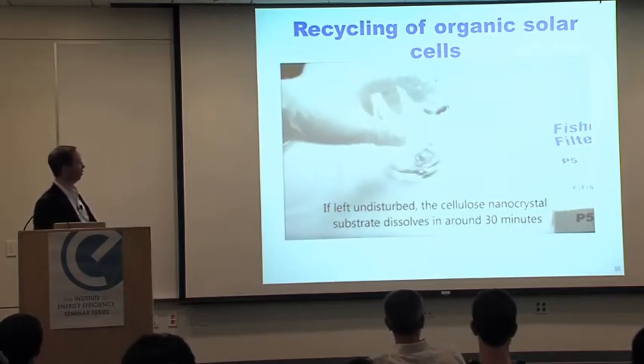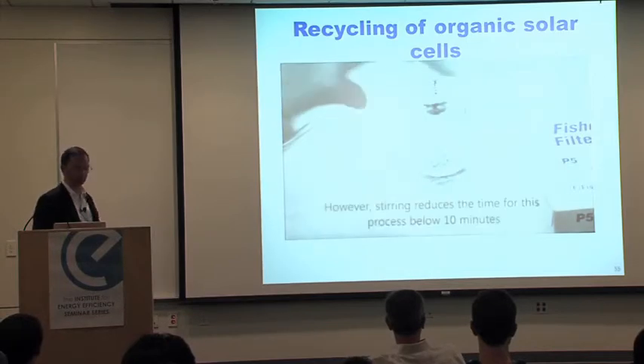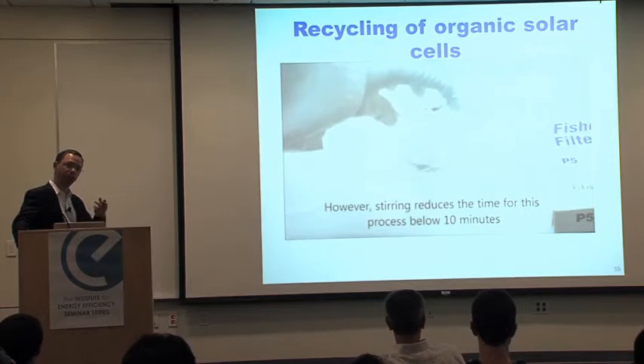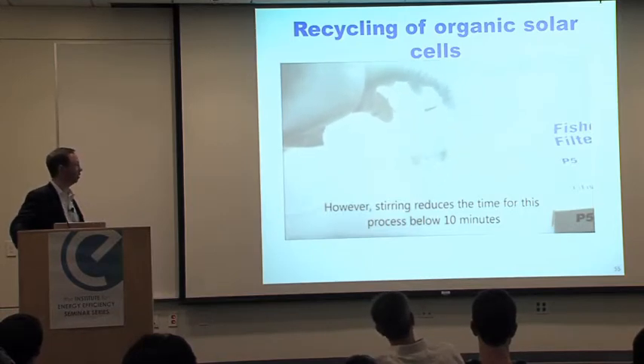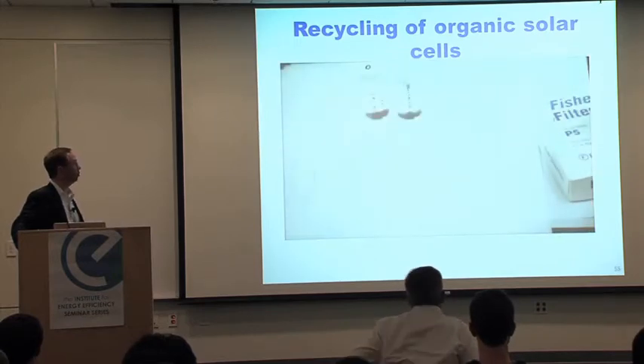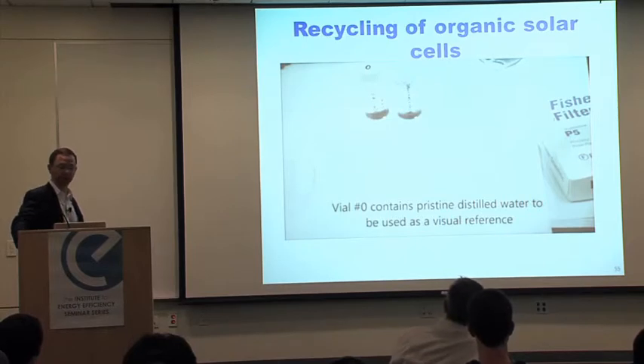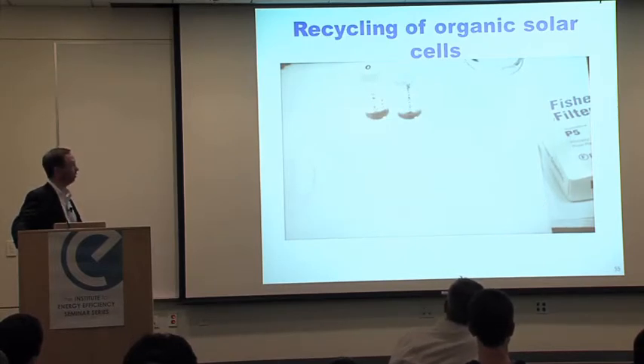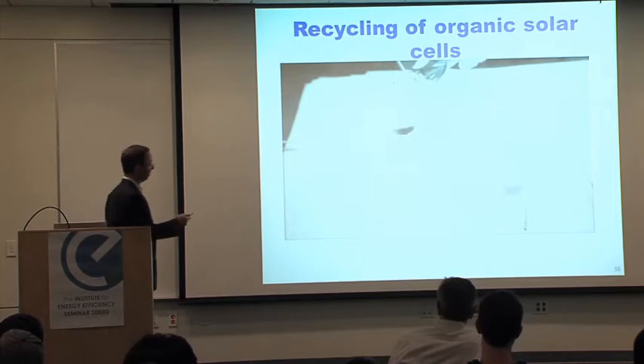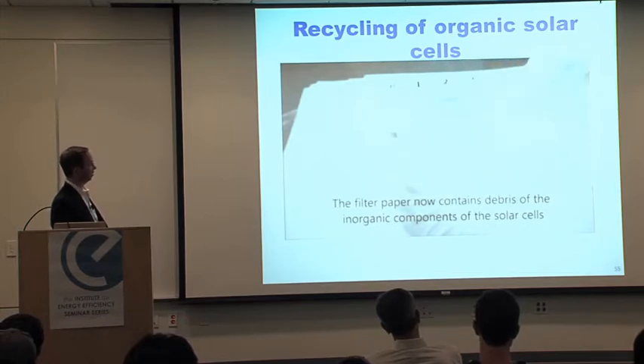If you take these solar cells [and place them in water], within a few minutes at room temperature, the substrate redissolves, and you [release the] thin active layer in that solution. So if you filter the solution, you can remove [the solids], and then what's left in that filter, if you use an organic solvent, you can recover also the active layer, which is shown in the next step here. You add now organic solvent, and you see from the coloring here, you're redissolving the active layer that was on the filter, and you'll end up with just the metal [electrode] used in that particular device geometry.